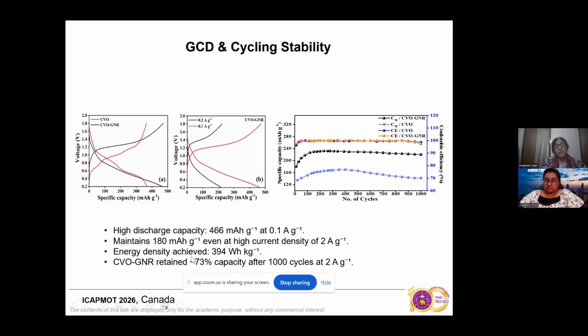And the energy density is also very good, so these are values which are comparable. But the only problem, on which we are working right now, is that it retained only 73% of the capacity after 1,000 cycles. So one has to really improve this value. That is, it should retain almost the same value even after 1 lakh cycles or 10,000 cycles and so on. It is maintaining good value at the lower current rates, around 0.1, 0.2 ampere per gram. But as the current density is increasing, these values tend to fall.